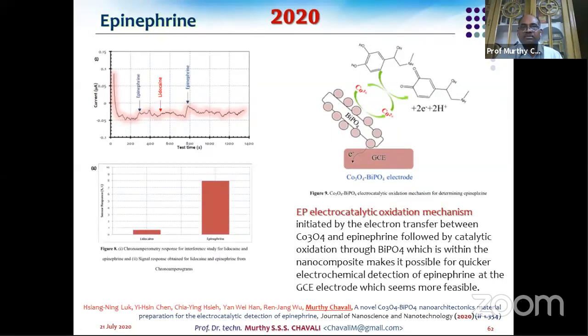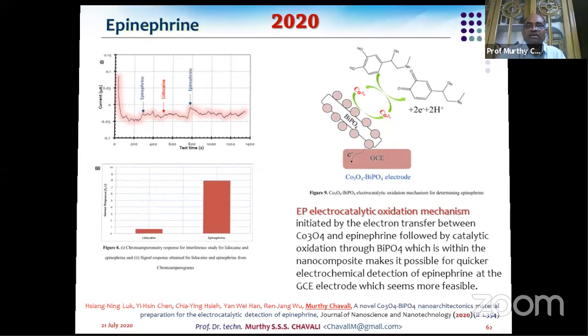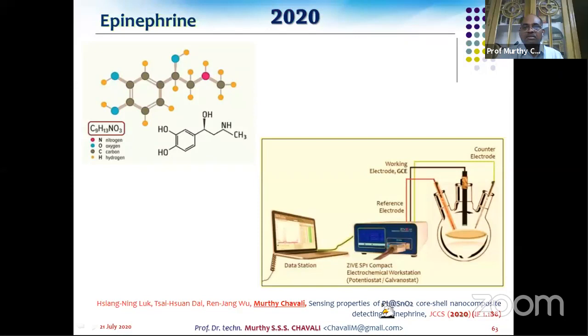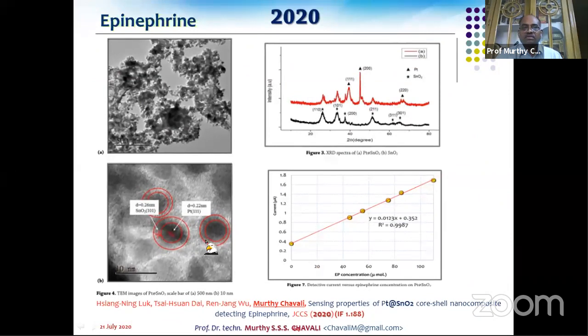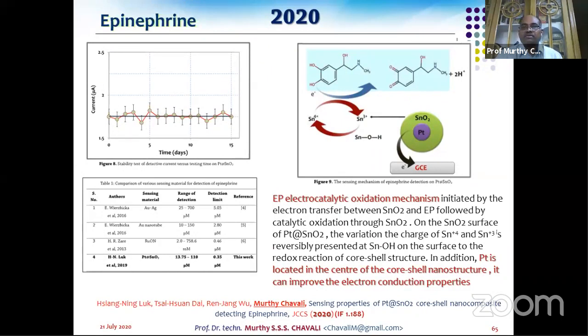And this 55 micromolar is not that competitive for the doctors, but they want to have enhanced sensors. So we developed another material, platinum doped tin oxide, as a core shell nanocomposite, so that the same epinephrine, using this particular material, we were able to detect. We were able to study these core shell nanocomposites, and typically we went up to 13.5 micromolar concentrations. Earlier it was 55 micromolar. Now we have come down to 13.5 micromolar, which is evidently required for studying the disease.